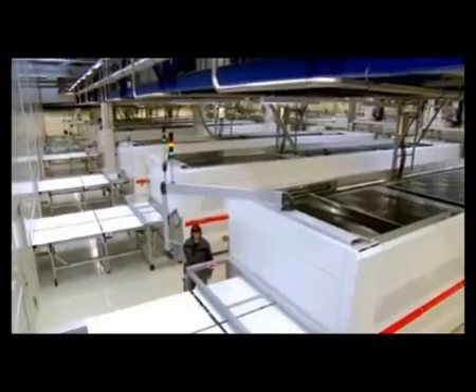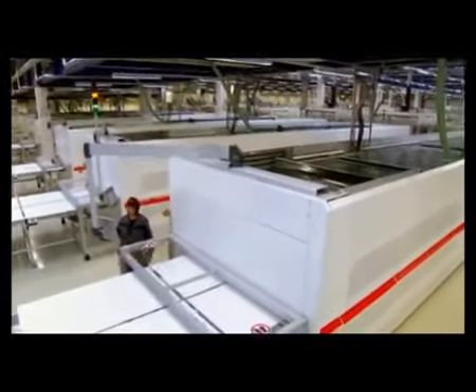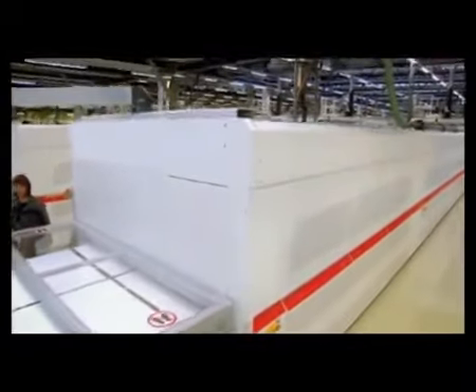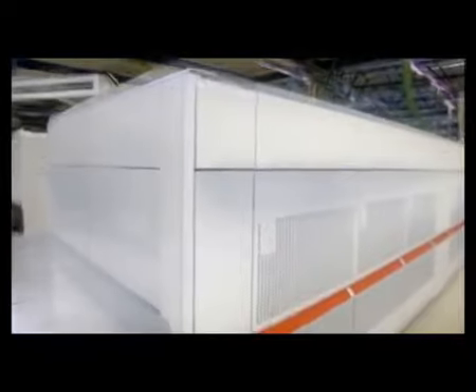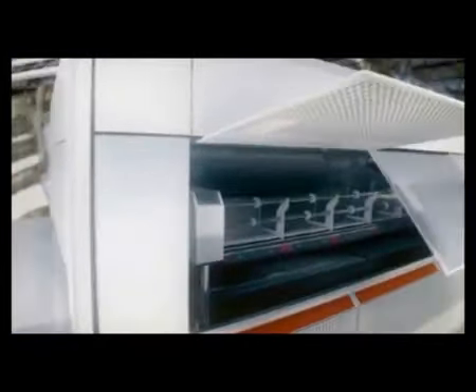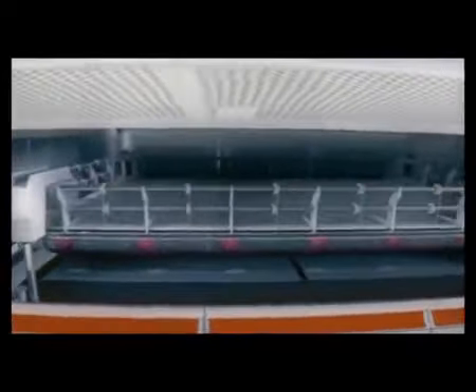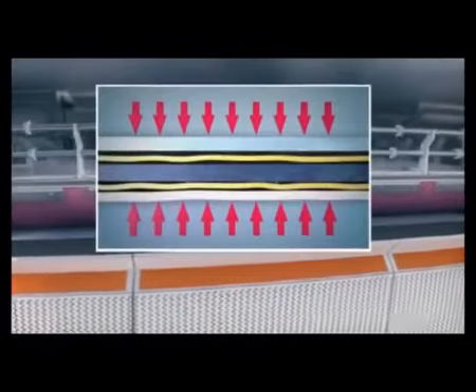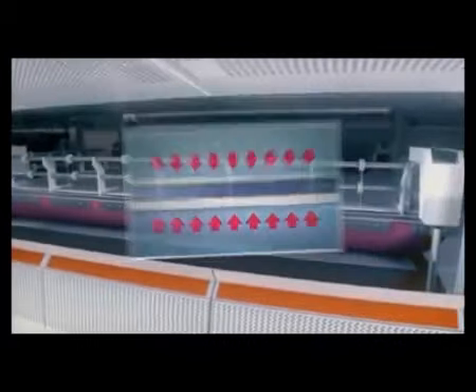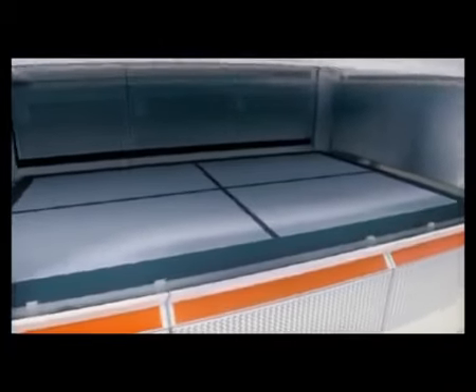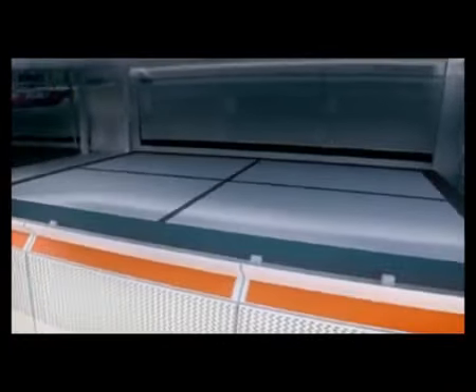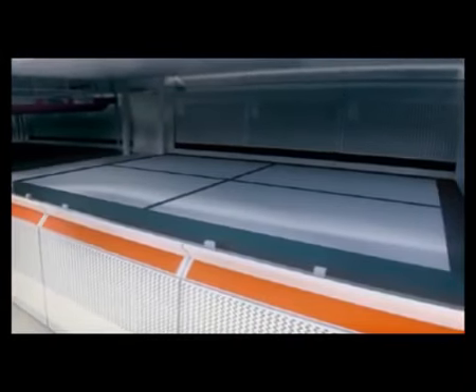Properly sorted into groups of 4, the modules are now laminated. A look inside the laminator reveals exactly how this works. Glass, films, and cells are warmed in a first chamber to approximately 150 degrees Celsius. In the second chamber, the EVA films are melted, while the air between the films is removed by a vacuum. Solar glass, solar cells, and films form the so-called laminate. The module cools in a third chamber, and after approximately 24 minutes, it leaves the laminator as a sealed, weather and shock-resistant unit.